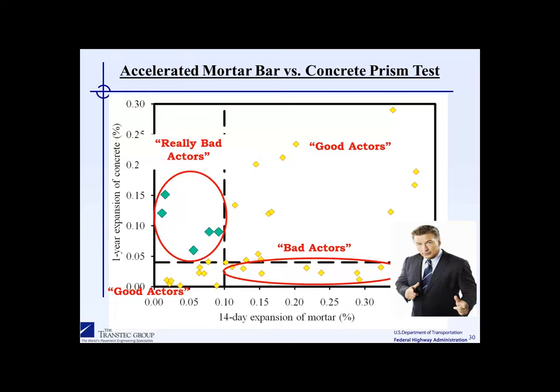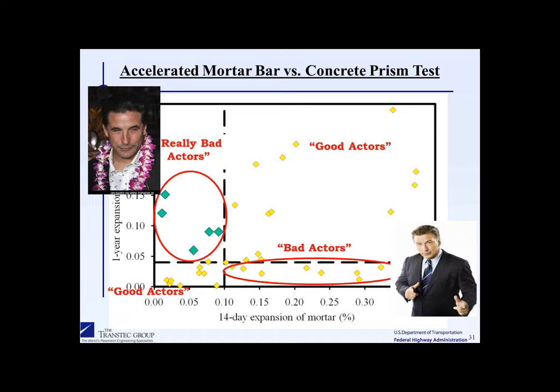However, what hasn't been known for as long, and it's really come to light in recent years, are what we're labeling here in the upper left-hand quadrant as really bad actors. And these are aggregates that actually pass the accelerated mortar bar test, but they fail the concrete prism test. Very counterintuitive that you would get this inverse relationship. These are what we call the really bad actors, or the Billy Baldwins of the world. And these are the most concerning because any aggregate that falls in this category, many specifiers and highway departments will consider these aggregates to be non-reactive, and they will not require any preventive measures at all for this situation.